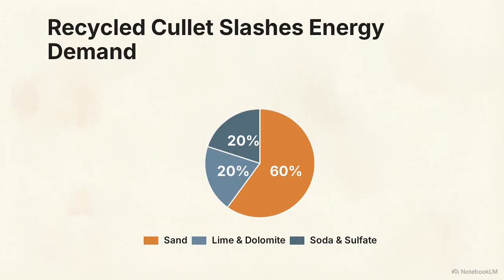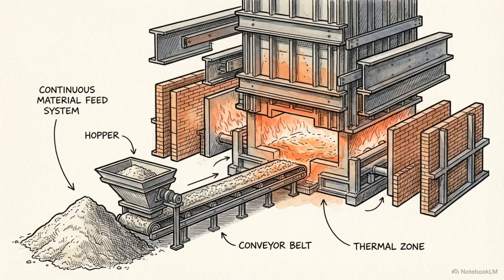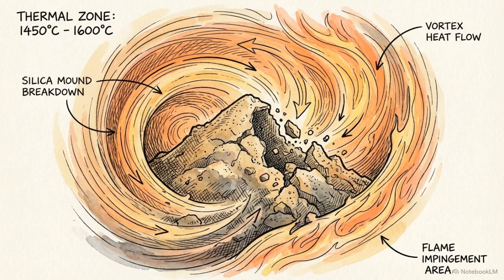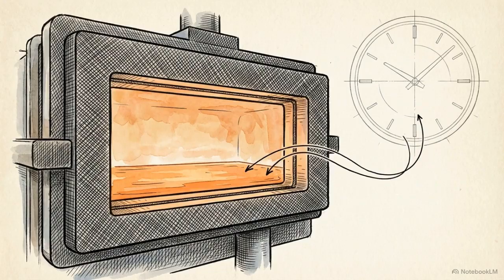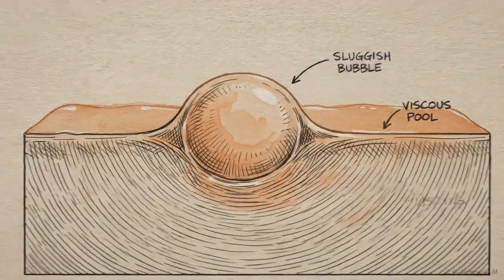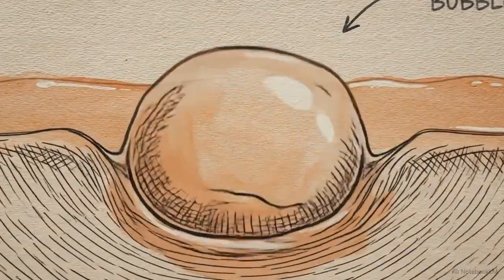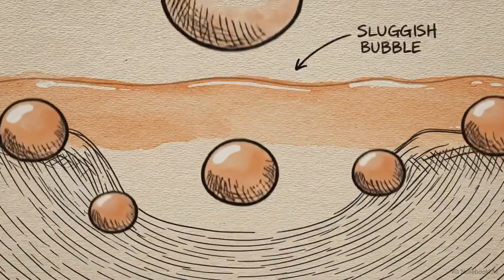This extra ingredient accelerates the melting phase and drops the total energy required to heat the furnace by up to a fifth. This highly specific batch is fed automatically into a massive furnace. Inside, natural gas combined with preheated air blasts the raw materials up to 2,800 degrees Fahrenheit. The mixture undergoes a continuous melting cycle that lasts up to 50 hours. This extensive heating period ensures the liquid glass is completely homogenized and free of any trapped air bubbles.